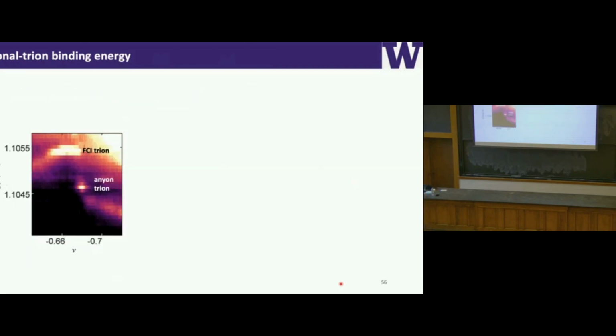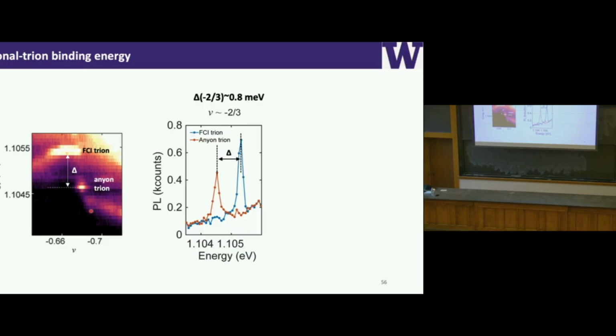Well, there's one way to do it. We can look at the energy difference between the FQAH trion and the anyon-trion. This energy difference corresponds to the binding energy of the state. So the binding energy means a quasi-particle binds to the trion to form this fractional charge bond. And the binding energy of this 2/3 state is about 800 microelectronvolts.